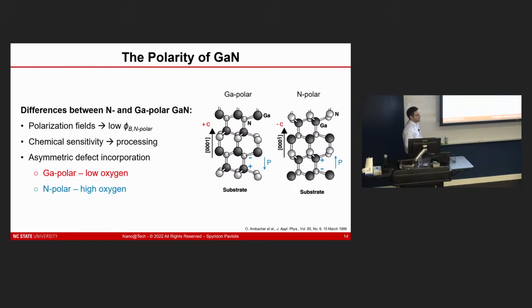Chemical sensitivity is very, very different for nitrogen polar GaN. So conventionally for GaN, you have to dry etch it, and you can expose it to a lot of different acids, and it'll survive quite nicely. Nitrogen polar GaN is very, very sensitive to acids and bases. I'll show a little bit of that later as well, but to make this clear, an early way of understanding whether you grew nitrogen polar or gallium polar GaN was just to dip it in KOH, and if you started seeing etching, it was nitrogen polar GaN. So it's that easy to see it.